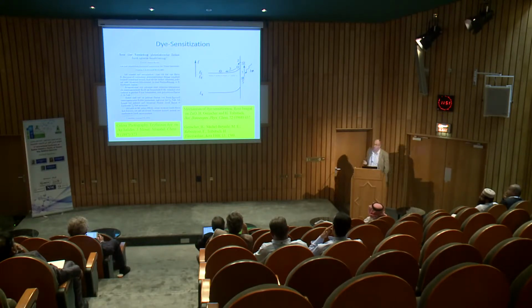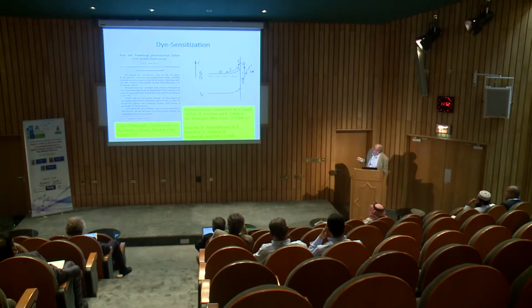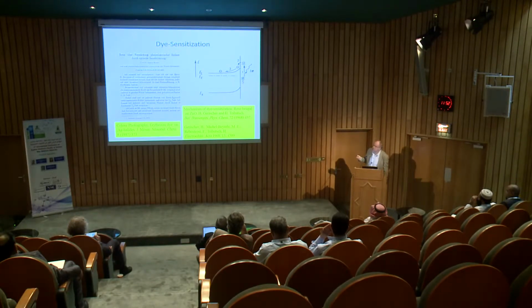And then it took maybe almost 100 years before people started to understand what is actually happening in a dye-sensitized system, and it's a lot thanks to Heinz Gerischer and his group with Helmut Tributsch at the end of the 60s, who presented the mechanism that we have a semiconductor, the valence band, conduction band. We have a dye anchored to the surface, and you excite the dye from the ground state to the excited state, and the electron is injected, and you can then measure a voltage and a current in an electrochemical cell.